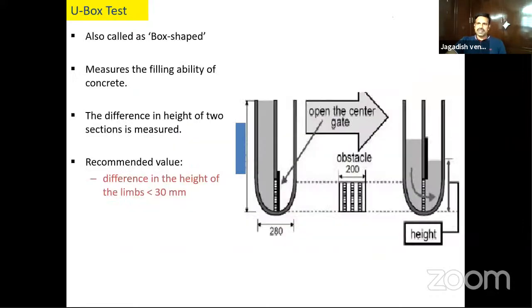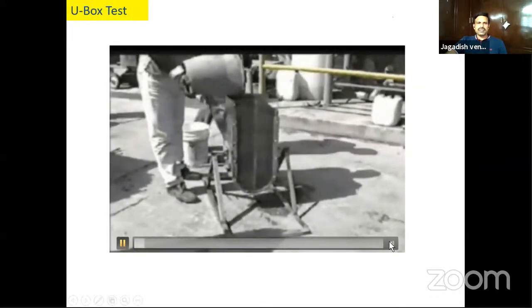There is also a measurement that is called U-box test. This also measures the passing ability, just like L-box. You fill one limb of the U-box with the SCC, and then you will open the gate and it will pass through the reinforcement, which is placed at the middle, and then the concrete comes into the another limb. So you measure the height difference in the two limbs. It should be less than 30 mm. This is how you measure.